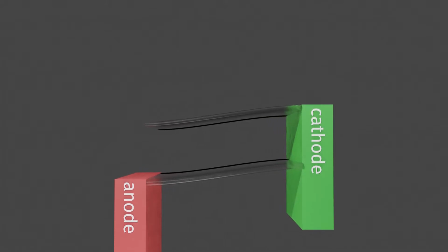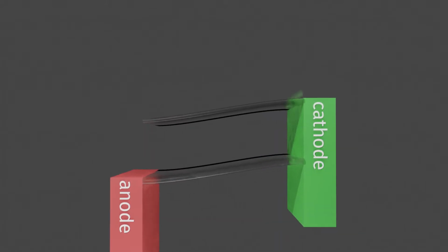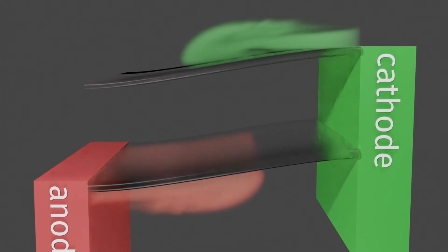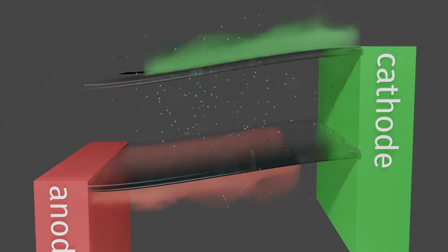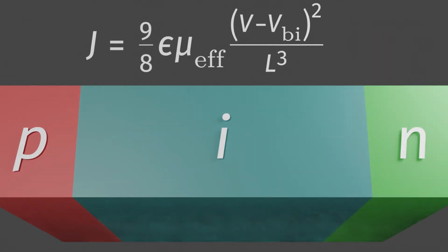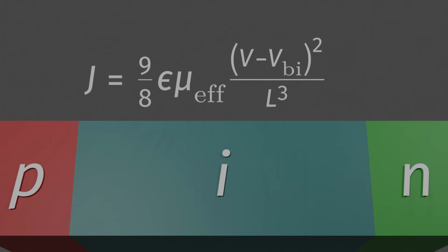Organic laser diodes are not driven by a diffusion current, but by a drift current, and the high carrier densities needed for lasing only exist under bias conditions. A higher bias results in more carriers, and more carriers reduces the resistance, hence space charge limited current. Similar to the unipolar case, that's more common, current is related to the square of the voltage and is described by the Mott-Gurney law. But in this bipolar case, the effective mobility comes both from electrons and holes and is enhanced by the recombination.